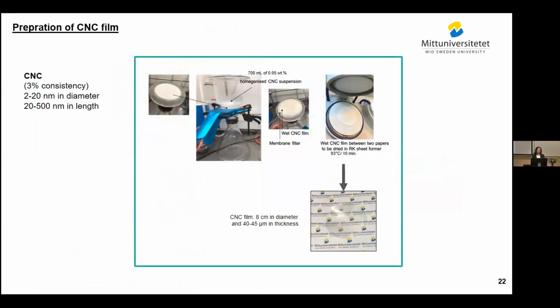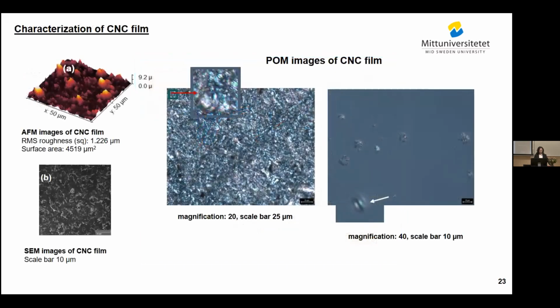We chose the filtration system to prepare the CNC film. For this, I transferred the well-homogenized and well-dispersed CNC suspension, 0.05 weight% prepared in water, to the filtration system. I waited 10 minutes until the draining of water stopped. It means that the first layer of gel formed. Then I connected the vacuum. After 16 hours, I got the wet cake of CNC film. After drying in a rapid Köthen sheet former, I could get a transparent CNC film.